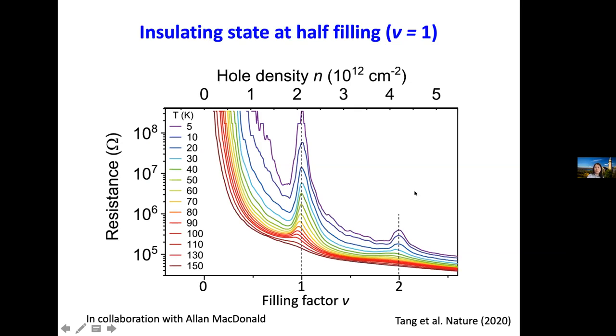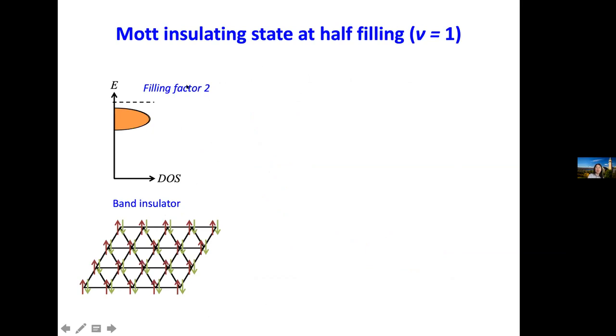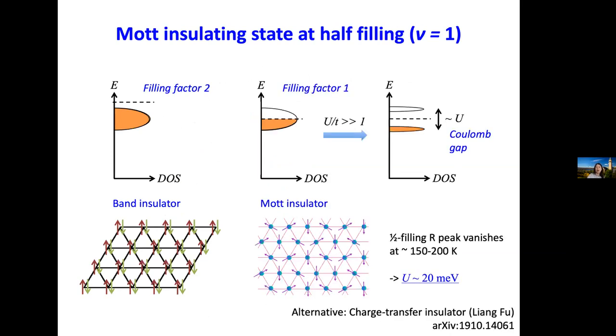We still have challenges there. You see two pronounced peaks, one at filling factor 2 and the other one at filling factor 1. And then they disappear when you warm up to a certain temperature. The insulating behavior at filling factor 2 is pretty well understood from the single particle picture. It's a band insulator. And the insulating state at filling factor 1 requires strong correlation. When the Coulomb repulsion is large enough, it costs more energy to put two charges on a single site. So a Coulomb gap on the order of U opens up, and this is a typical Mott insulating state picture.